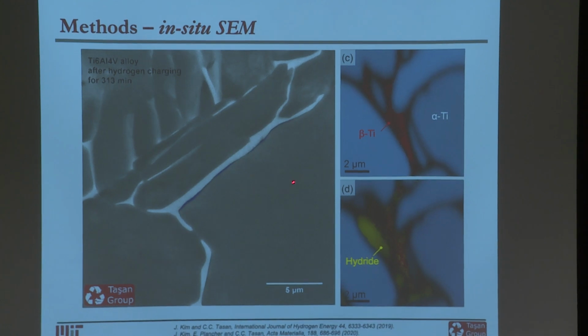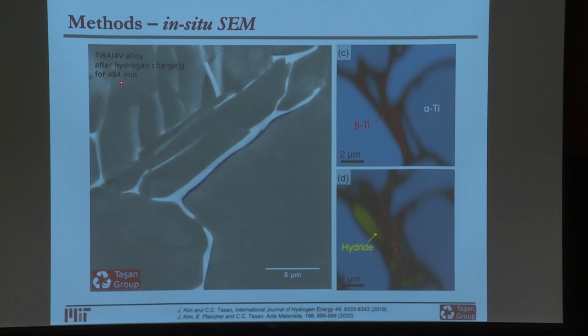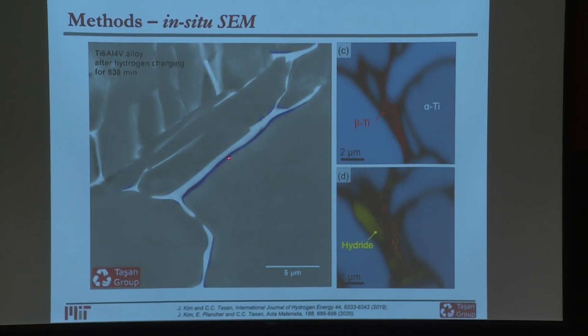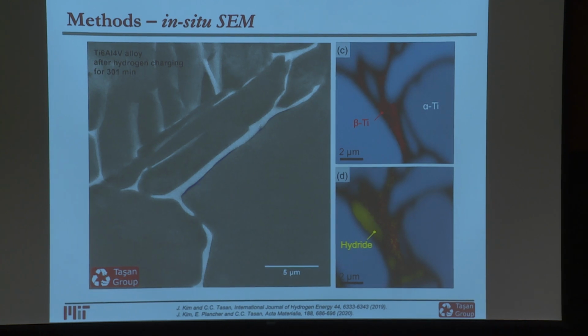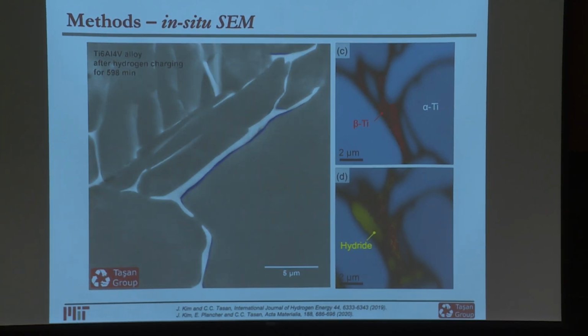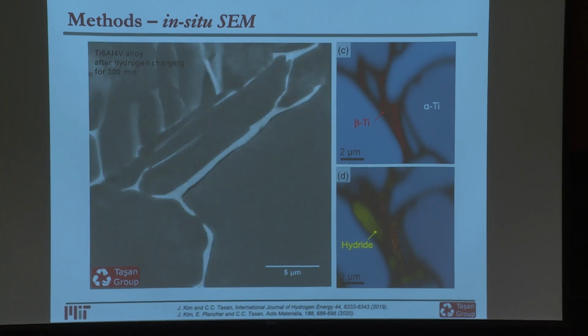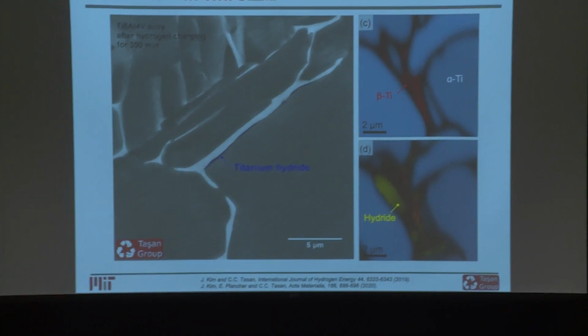So we are looking at Ti-64. If you look carefully, time is evolving, and you see this hydride forming at the intersection, at the phase boundary between the beta phase and the alpha phase. That's this blue region. And then you can switch to electron backscatter diffraction, EBSD, to actually analytically prove that it's the hydride phase that's forming. So the synchrotron diffraction analysis told us something that's more about an average response. And it's a time-resolved response.